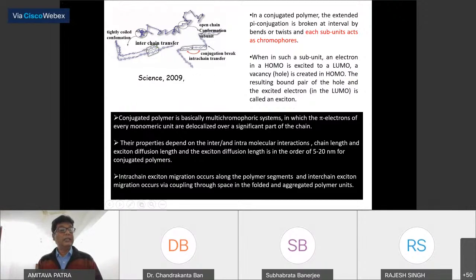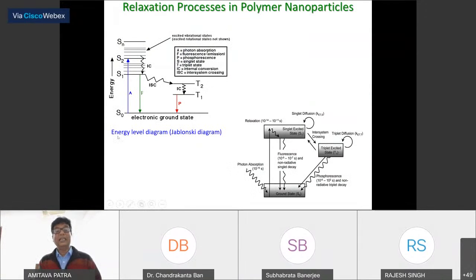So what happened here, there are a lot of antenna molecules here, so a lot of photons can be absorbed by individual chromophoric units, because conjugated polymer is basically a multi-chromophoric system where pi electrons are very much delocalized over the chain length, because if you increase the chain length, you can tune the exciton diffusion length and all relaxation processes. So you know this energy level diagram, Jablonski, because of the molecular system, the S0, S1, S2, Sn state, right? I'll show you the difference of relaxation process when it is aggregated structure or polymer nanoparticle. That I'll show you, the exact we have measured for different systems.